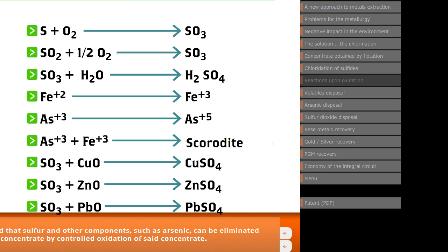Besides oxidation of sulfur, important reactions take place during the controlled oxidation. In the presence of metal oxides, such as copper oxide, that are good catalysts, the initial sulfur dioxide is oxidized in part to sulfur trioxide that leads to sulfuric acid. Also, some of the arsenic, iron, antimony, and bismuth are oxidized to their higher valency, leading in the case of arsenic to the formation of ferric arsenate. This chemistry is complex and substantial.